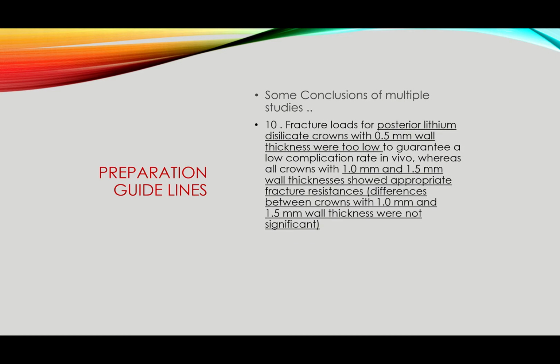Now the last one, fracture loads for posterior lithium disilicate crowns with 0.5 millimeter wall thickness were too low to guarantee a low complication rate. So 0.5 millimeters for lithium disilicate showed a failure. Whereas all crowns with 1 millimeter and 1.5 millimeter wall thickness showed appropriate fracture resistance in lithium disilicates as well. So once you increase it to 1 and 1.5 wall thickness, you're doing good.